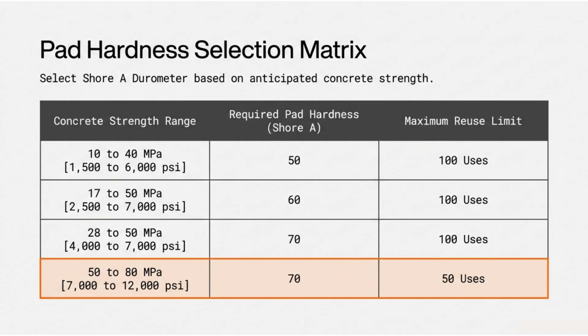Here's the matrix shown. 10 to 40 megapascals, 1,500 to 6,000 psi: Shore A 50, max 100 uses. 17 to 50 megapascals, 2,500 to 7,000 psi: Shore A 60, max 100 uses. 28 to 50 megapascals, 4,000 to 7,000 psi: Shore A 70, max 100 uses. 50 to 80 megapascals, 7,000 to 12,000 psi: Shore A 70, max 50 uses.